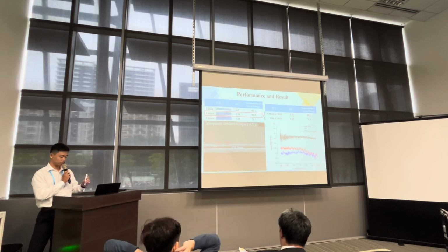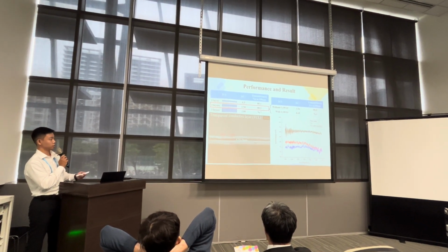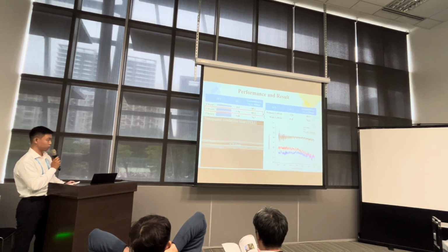So we use 2 double-layer configurations to create a conductive layer with and without cesium tungsten oxide. As you can see, the sample with the cesium tungsten oxide actually has a lower resistance, and both samples have a similar transmittance in the visible light.